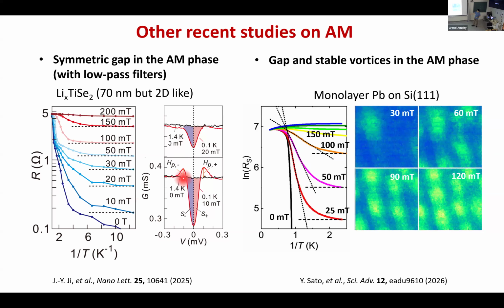So actually, next week I want to mention this, that recently we also measured a very thick film, lithium intercalated titanium diselenide. We see the anomalous metal phase. We claim it is still 2D, although it's very thick, but from the anisotropy it shows 2D behavior. What we observed recently is the superconducting gap still persists in the anomalous metal phase. In this anomalous metal phase, we still see the gap and it's symmetric. We try to say it's consistent with the picture that you have electron-hole symmetry.